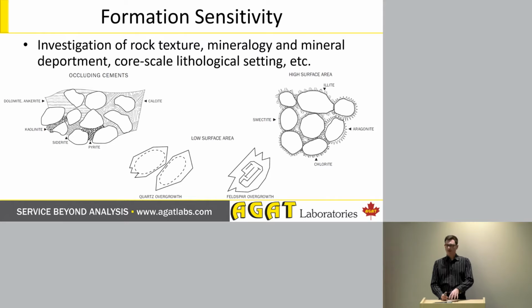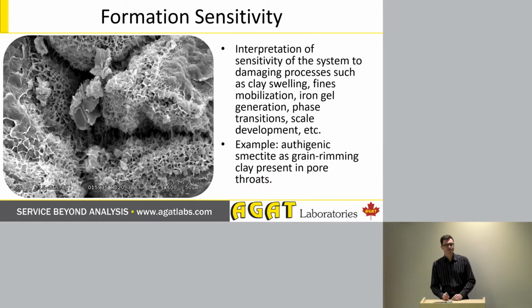What we're going to look at is the rock texture, so that's the mineral deportment as well as overall mineralogy. We're going to look at core scale lithological setting if we can. If we have a core, we'd love to be able to have a look through the core and identify zones of interest of likely low risk and higher risk. We're going to interpret the sensitivity of the system to damaging processes, such as clay swelling, fines mobilization, iron gel generation, and phase transitions. This example here is an authigenic smectite, grain-rimming clay, mineralized right into a pore throat. So this is a really great example of some of the potentially damaging situations we see.